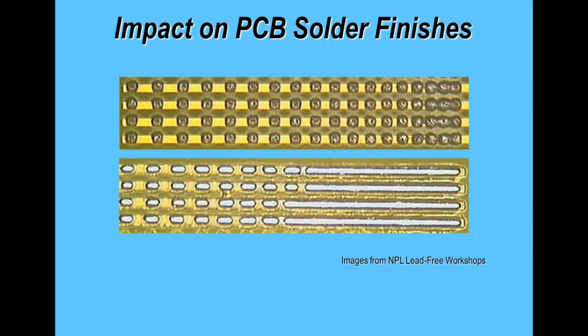And basically what we're doing is we're printing dots of solder paste when you're producing your boards, and the dots of solder paste are placed along specific tracks on a spare area of the printed circuit board. And during reflow, because the dots are a different space together, when they wet, they coalesce. But obviously, depending on the solderability or wettability, some dots do not coalesce. And that gives you a measure of solderability on a specific finish with a specific paste on your board finish.